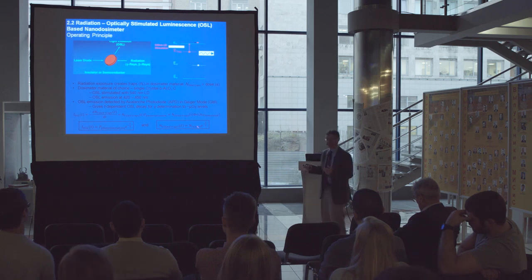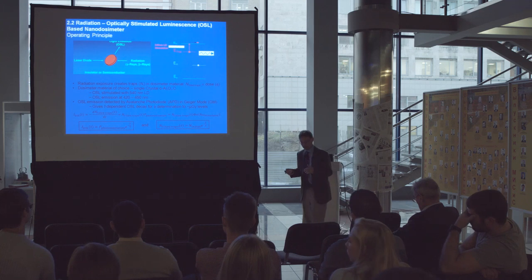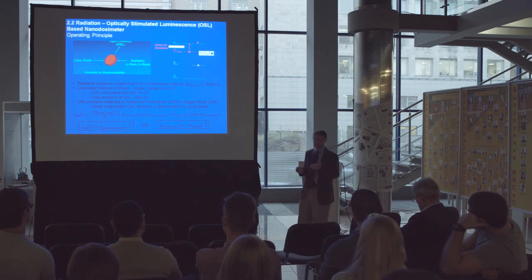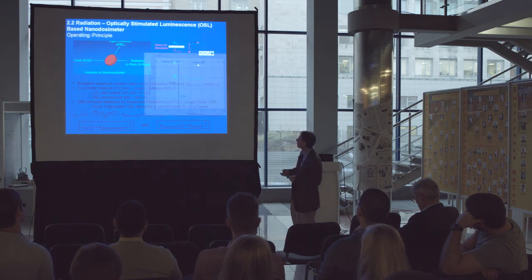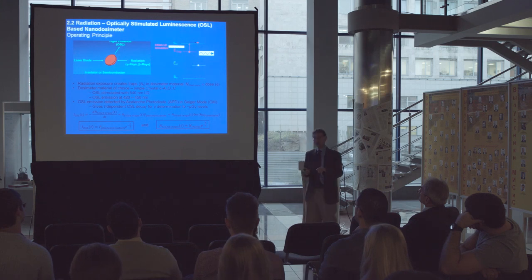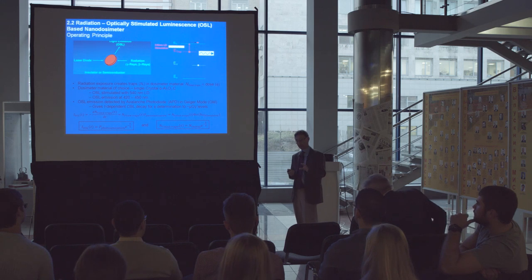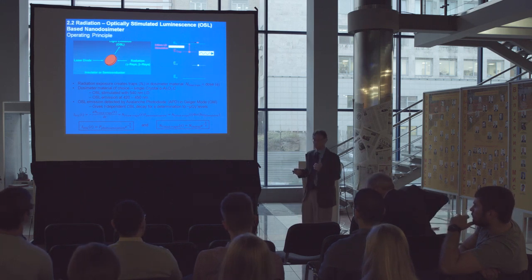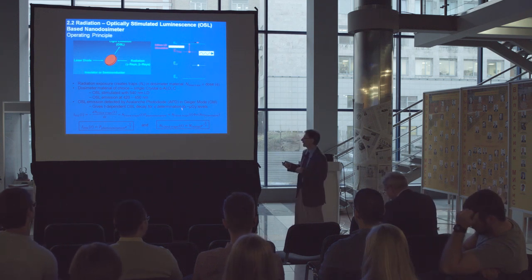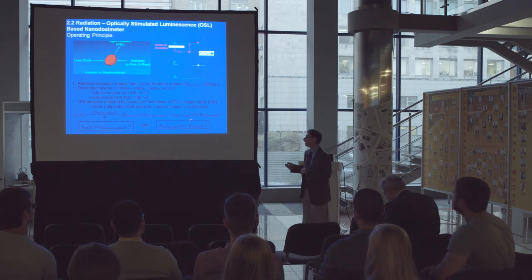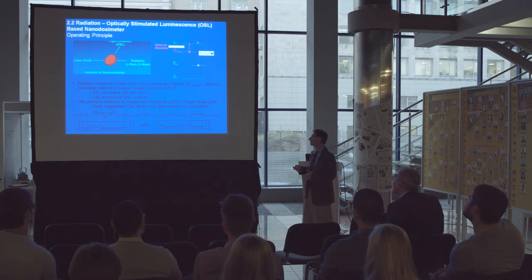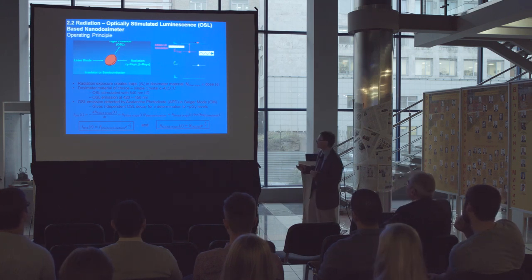And of course, by recovering the tau for the process, we can use this equation to calibrate for the amount of radiation dose that this sample has seen, the number of traps, N naught, the initial number of traps in the material from exposing it to radiation. One last point is, in order to measure the amount of exposed radiation this sensor has seen, we need to detect individual photons, right? The problem is how to build, for this particular wavelength range, which turns out to be where silicon is horrible, an avalanche photodiode, which is a single photon sensor that can be gated on the time scale of this luminescence process to count the photons. And the better we count, the better we can tell the dose. Okay, so that's the problem and what we want to do.